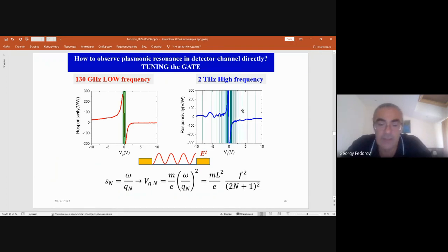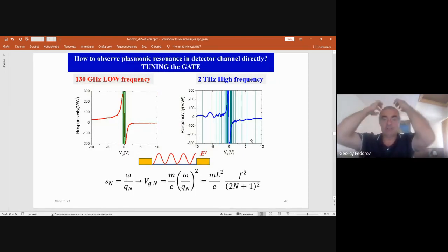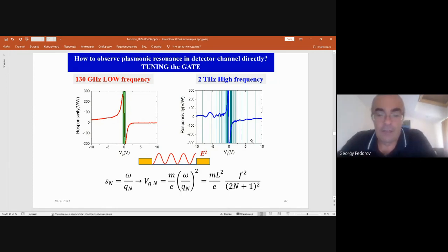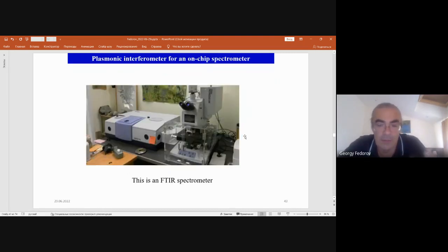they are there, and it is easy to understand why we don't see anything at low frequency, because these peculiar values of gate voltage scale as the square of the frequency. So at low frequency we see nothing, at high frequency we see many modes. We are supposed to see many modes of resonance in this device, and the positions of these resonances are matching the theoretical predictions. And I don't have the slide illustrating that, but still I move on with this story, because what we have,